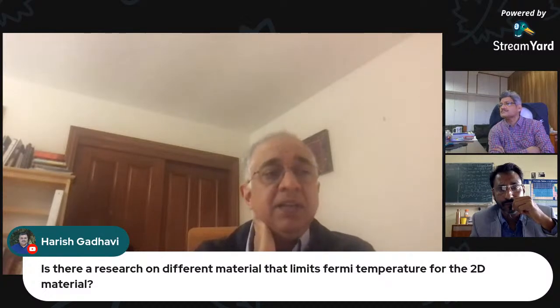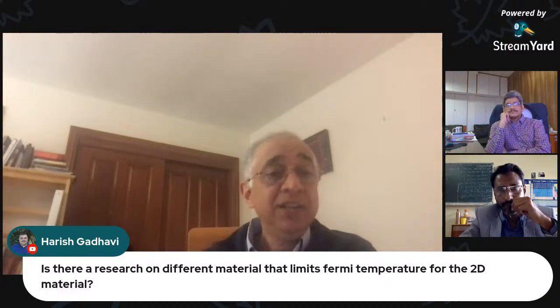Okay, so the thing is, the Fermi temperature in any material, 2D or 3D, is generally very hard to change in metallic systems. Because you can't change the electron density, therefore it's very hard to change. So the places where people have changed Fermi temperatures in 2D materials are ones which can be gated. Because with gating, you can actually change the electron density. So you could see that, for instance, this ionic liquid gated material, they could change. You can go and look at this.